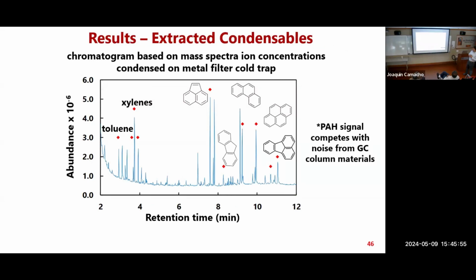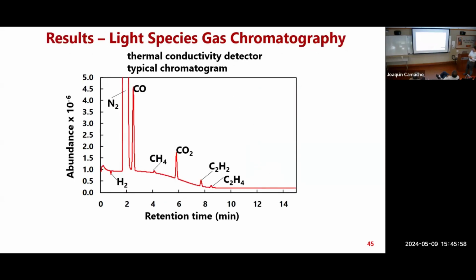But the challenge we're having now is the O2. It's very hard to quantify that from this method. It comes right next to the nitrogen. It probably would be present in fuel lean flames, and here it probably is there as some noise peak, because it's very hard to make this leak proof. It wouldn't be from the flame, it would be from contamination. I do see it sometimes if we have leaks. It's very hard to avoid the O2, but it's not from the flame.